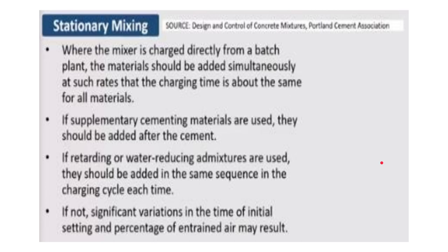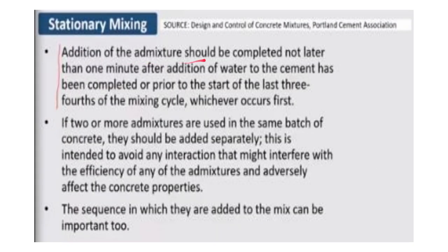Addition of the admixture should be completed not later than 1 minute after addition of water to the cement has been completed, or prior to the start of the last 3/4 of the mixing cycle, whichever occurs first. So this has to be kept in mind.